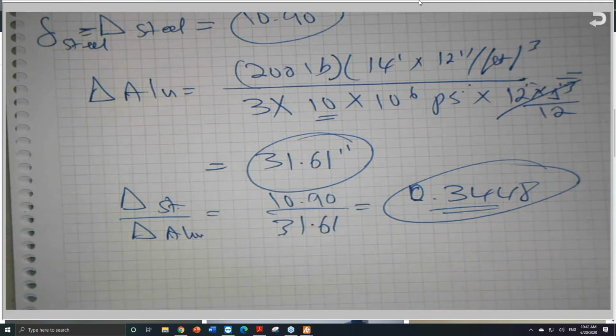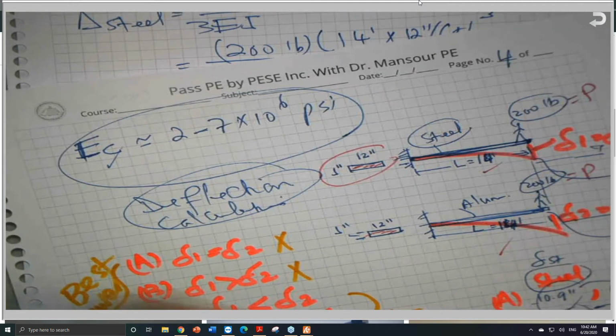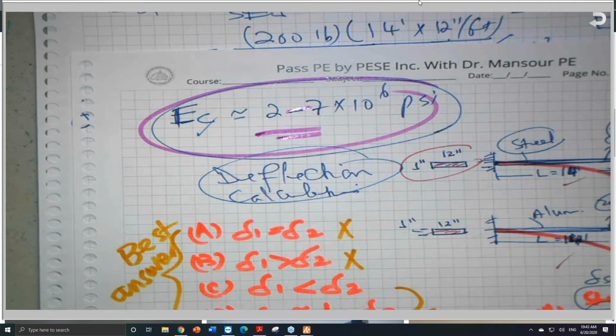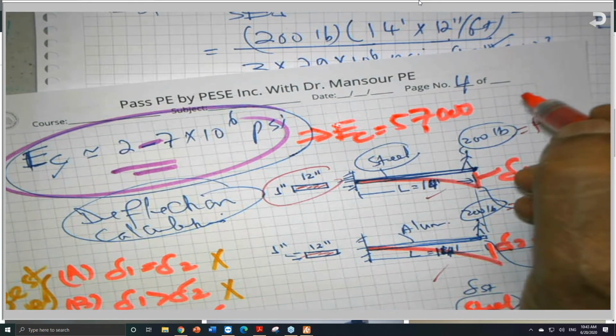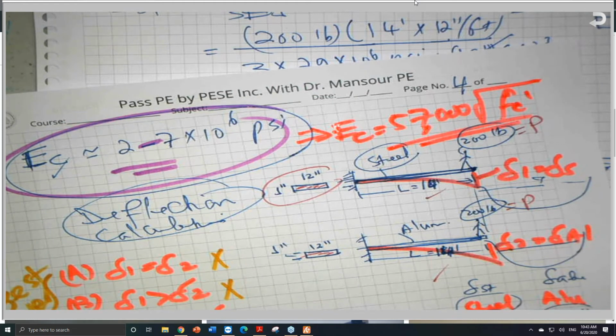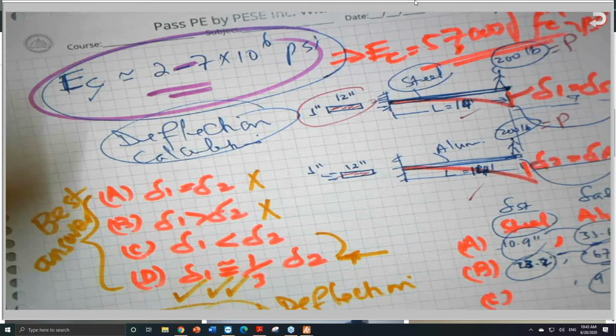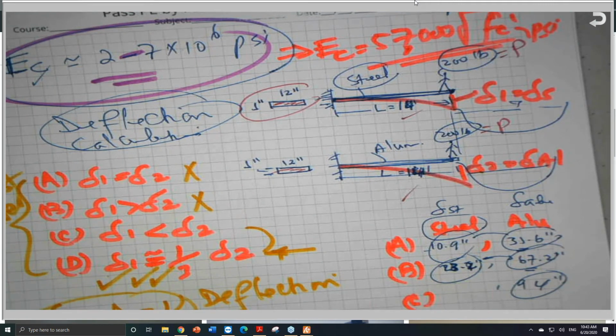So the modulus of elasticity for concrete, the number we said is between 2 to 7 million psi, is a function of f sub c prime. And as I said, the empirical formula that ACI developed for us is E sub c equal to 57,000 square root of f sub c prime. This is the empirical formula, and the modulus of elasticity will come in psi. It must be in psi, by the way. And don't tell me it's under the radical, so the units will not matter. This is an empirical formula, so units are not really an important parameter in empirical formulas.